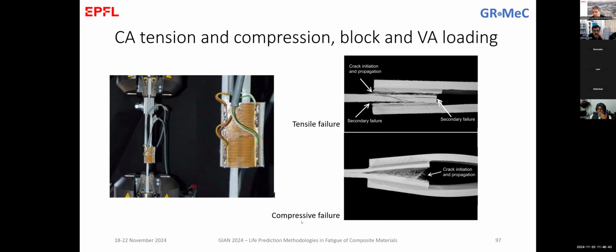But then when we go to compressive failure, you see that the material started failing in the middle. So here, I didn't describe the material before, but the adherents that were used were pultruded elements that had in the middle unidirectional layers. So actually here the material failed in a mode 1 condition of this internal layer. And this was due to the compression, these two elements buckled and opened like this. And the interesting thing is that the mode 1 fracture behavior of the adhesive, so at this region where we have the adhesive joint, was much better than the mode 1 performance of the adherent itself, so the composite itself. And this is the reason for having the failure, so the crack initiated in the middle instead of initiating somewhere in the edges.